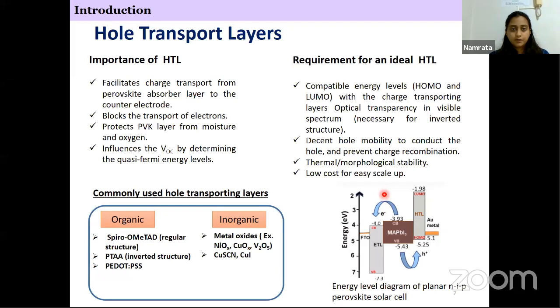The underlayer or the HTL in the inverted device architecture facilitates charge transport from the perovskite absorber layer to the counter electrode. It blocks the transport of electrons, protects the perovskite layer from moisture and oxygen, and influences the VOC by determining the quasi-Fermi energy level. So to have an ideal HTL, it should have compatible energy levels, like the HOMO and LUMO, with the neighboring charge transporting layers. It should have optical transparency in the visible spectrum, which is quite necessary for the inverted structure. It should have decent hole mobility to conduct the holes and prevent charge recombination, and should have high thermal and morphological stability. And of course, like everything, we need to reduce the cost. It should be less expensive, so that we can have an easy scaling up of the technology.